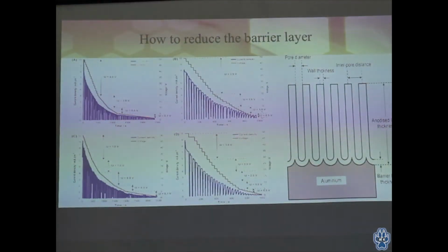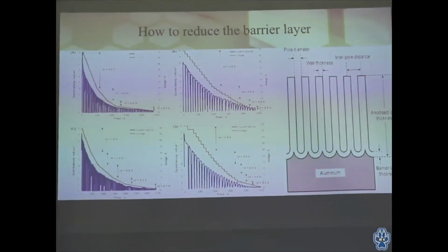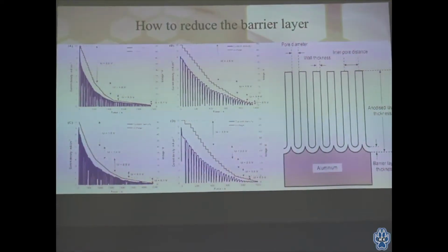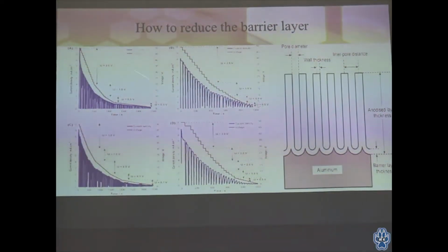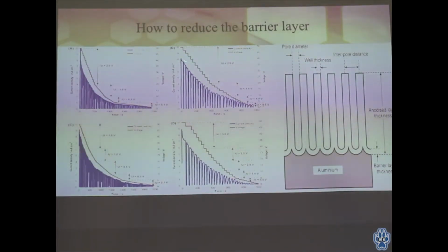So the next step after having these highly ordered pores is we want to reduce the barrier layer. We did two different things to reduce the barrier layer. One was we implemented a voltage drop, which is indicated by this red line after the third voltage. So we would lower the voltage from 40 volts to 10 volts with a step size of half a volt for roughly 20 minutes. What this does is, it is indicated here by the blue line, which is the current response during a voltage drop, it basically disturbs the equilibrium of the oxidation reduction reaction that is occurring, causing the oxide to be consumed during the reaction.